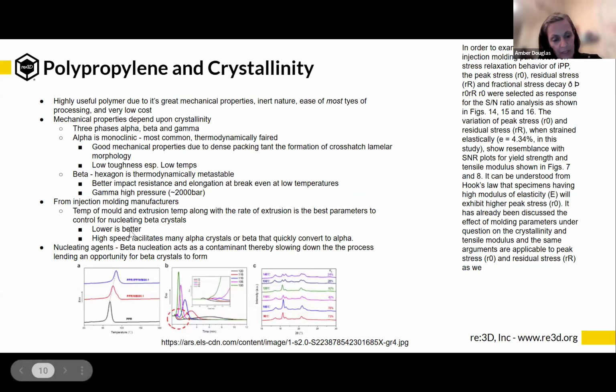And I think mostly what I started studying and what Chris looked at as well was the injection molding. And what they pretty much exclusively say, you can pull up 20 papers and they all say the same thing, is to control the mold temperature and the extrusion temperature and just decrease it. The lower, the better, if obviously you want to have some flow. They have the benefit of having pressure because they push it, but we don't. So we have the extrusion temperature that's coming out. We can control the temperatures, but the lowest you can get it without it getting too hard, the better. Then the mold, for us, that wouldn't be the mold, right? It would be the bed.